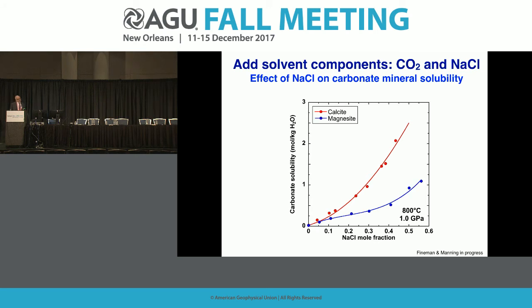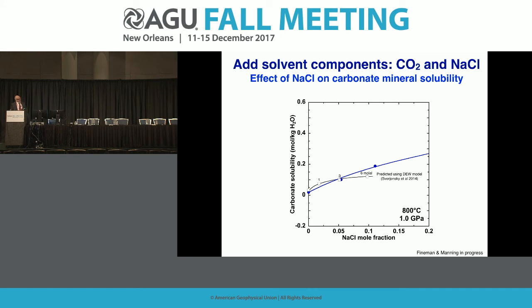Other carbonate minerals behave differently. For example, here's magnesite, and you can see that the data describe more of a quadratic sort of form. And in fact, if you look carefully at our calcite solubility fit, it departs significantly from the fit in the exact same region, in this low NaCl region, where it seems likely that we've simply adopted an inappropriate functional form to generate that fit. And the interesting thing is that the topology of the curve, which we see experimentally in blue, is sort of predicted. The quality of the fit, it's not great, but the form is similar when we do this theoretically using the DEW model. There's a strong increase in solubility with a small amount of NaCl, and then it tails off as you increase concentration of NaCl to higher values.